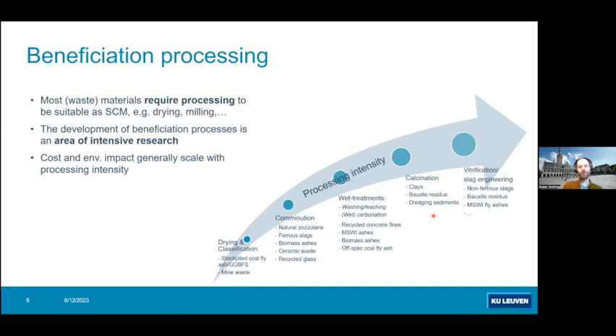In general, if you look into what processes are being used, they could be classified as a function of their processing intensity. We can have fairly low intensive processing, such as drying and classification methods, which are used today. Comminution, also fairly common to the industry. Of course, when we have natural pozzolans or slags, we might need to mill them to some extent. But there's more intensive processing also being explored.